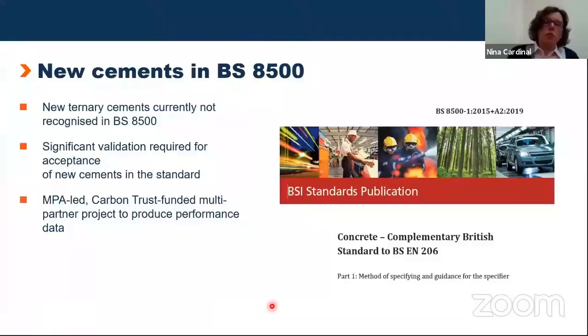So currently, these new ternary cements, which will be in part 5 of the cement standard, are not yet recognized in BS 8500. There is usually a significant validation program required to gain the acceptance by the committee, which agrees to the changes to a standard. The Mineral Products Association led already 2 years ago started a program which was funded by the Carbon Trust and involved a number of cement and SCM manufacturers in the UK to produce data to demonstrate the performance of the new ternary cements, which we expected to come our way.